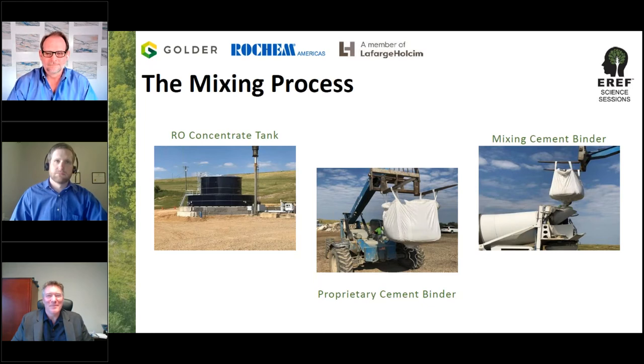Now, since there was no textbook on how one goes about encapsulating PFAS in RO concentrate, the first page of that textbook was written at lunch with Paul Scrisha, when we started scribbling down notes as to what a successful test might look like. That led to an initial attempt at about 42 different blends of cementitious pozzolanic materials, whittled down to about 21, and then finally settled on about 5. From that, we selected what you see in the middle picture, a pre-made, pre-blended proprietary binder that was then loaded into that ready mix truck that you see.